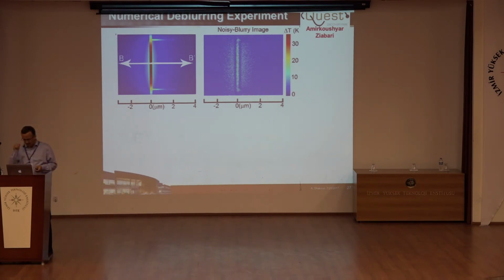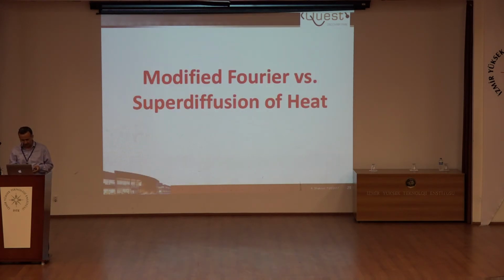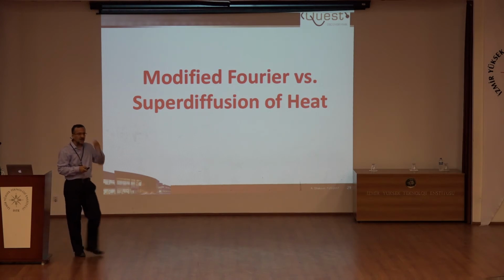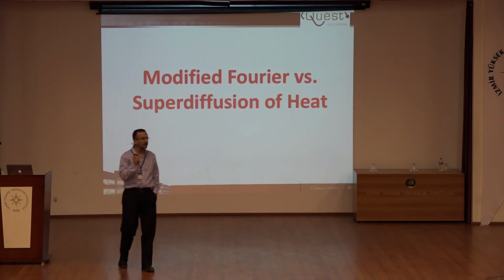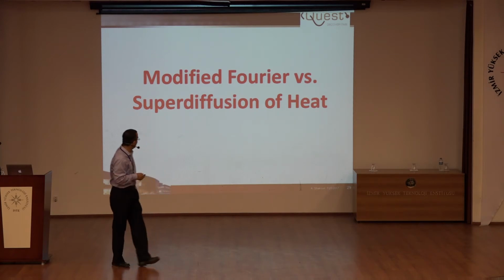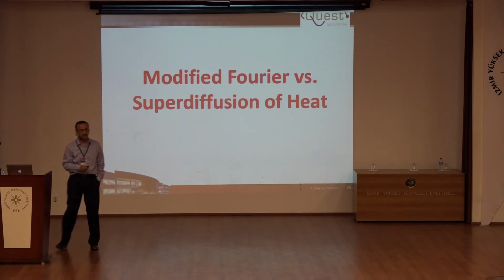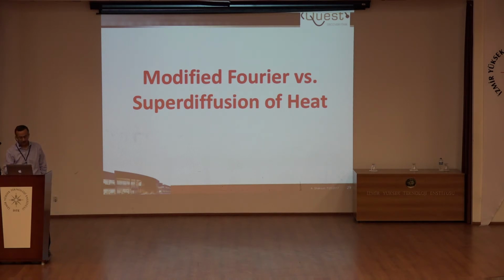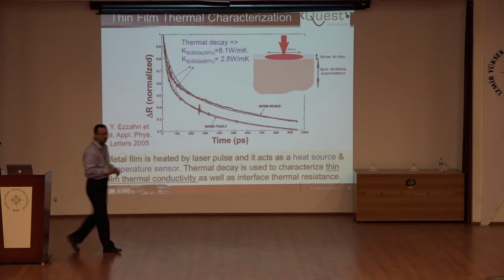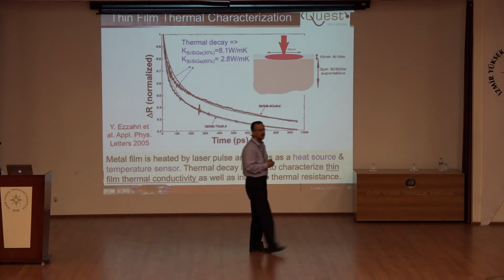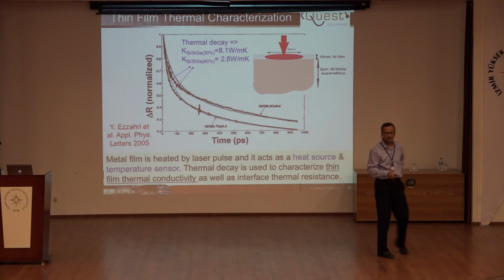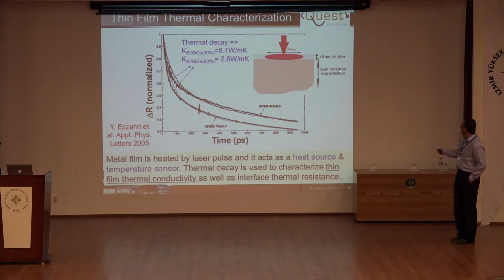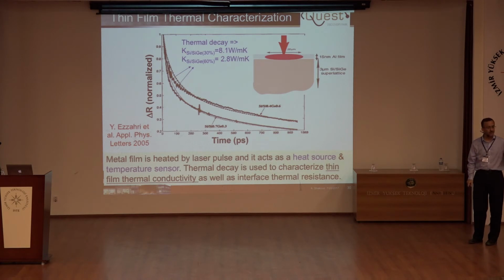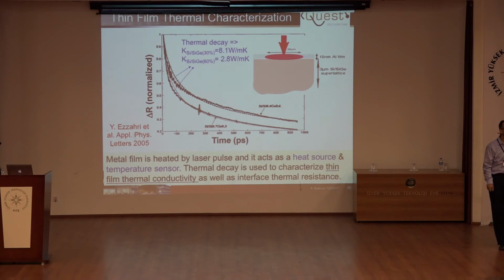So let me now go to the second part of this. This hydrodynamic effect is one of the things that happen at the smallest scale. But there is another thing that happens, which is modified Fourier, that I want to go over, that is of a different nature. First of all, I should tell you how we measure thermal conductivity of a very tiny film. In this case, we have a 3 micron superlattice, silicon and silicon germanium. 3 microns is 1/10 of a human hair thick. How do you measure how much thermal conduction it has?